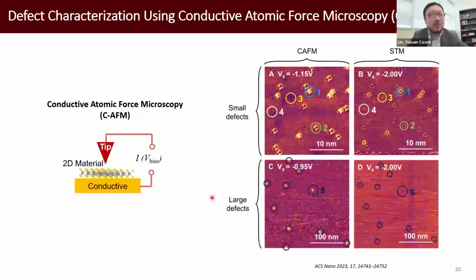The particular approach we are focusing on is called conductive AFM, or CAFM. It's very similar to AFM, but we use a conductive tip, and we scan along the material, and we measure the out-of-plane conductivity, so we can get this kind of mapping.